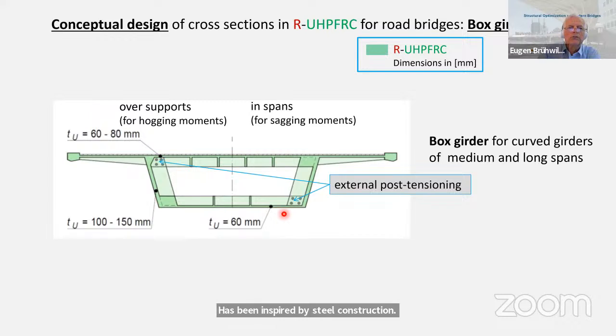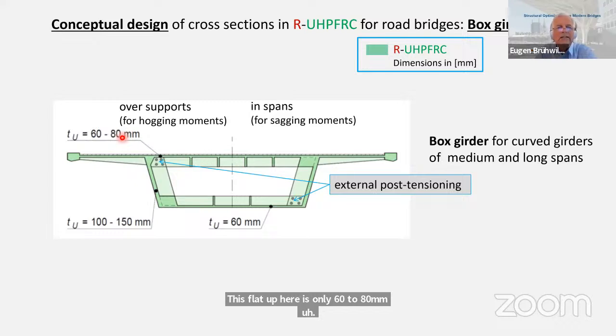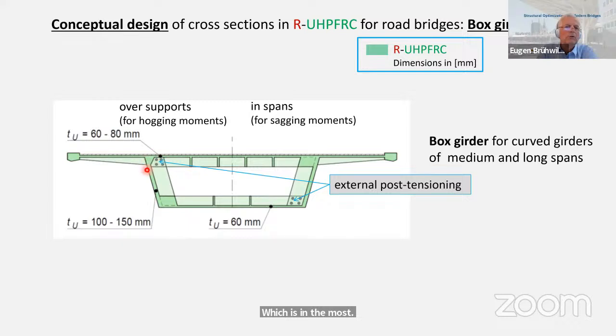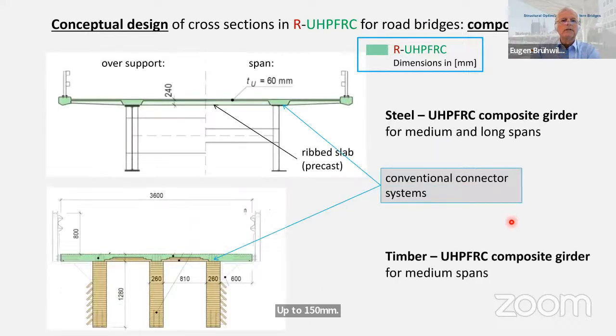Here we look at the box girder, again with ribs in both directions. The slab up here is only 60 to 80 millimeters thick, or thin, rather more. Of course, we use post-tensioning, which is in most cases external post-tensioning, because we want to keep the web as thin as possible, up to 150 millimeters only. So this would be for box girder.